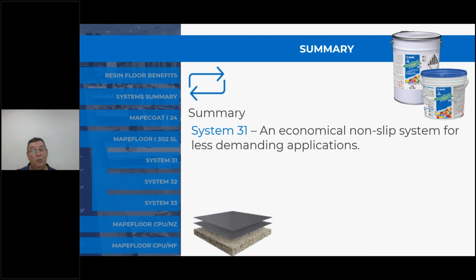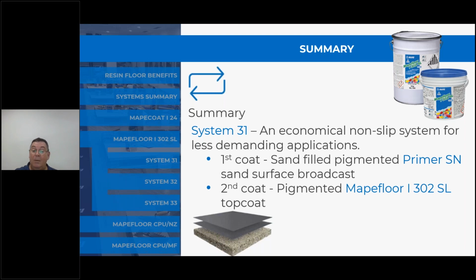System 31 is the most economical non-slip system for less demanding applications. One coat of pigmented primer SN broadcast, and a second coat, a sealer coat with the Mapefloor I-302 SL as a top coat. There is also a System 34, which I haven't mentioned, but that is also for less demanding applications, where two coats of I-302 are applied much in the same fashion as the I-24 directly onto the prepared concrete without a primer.